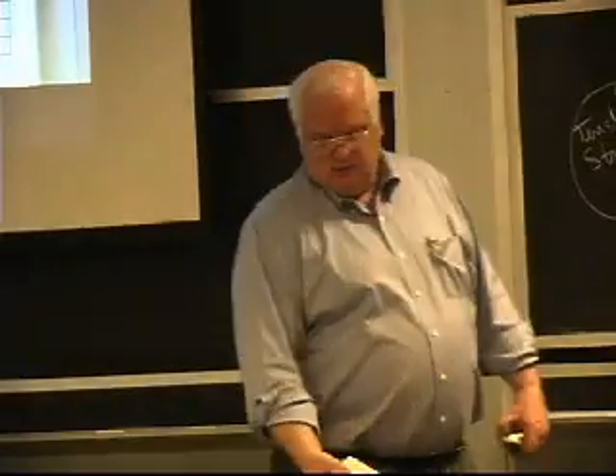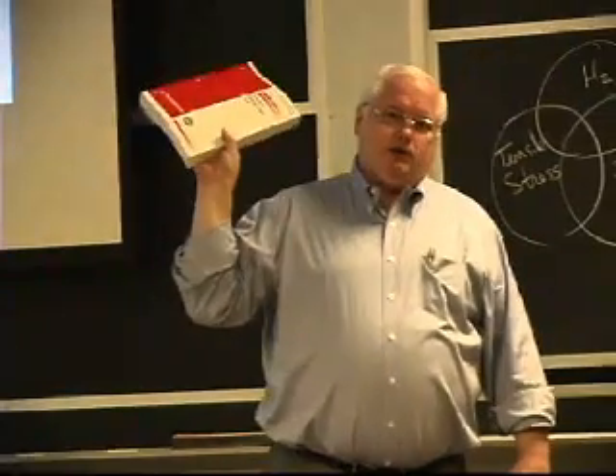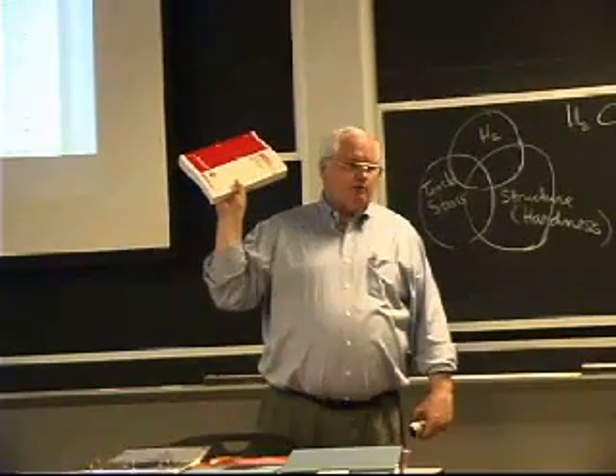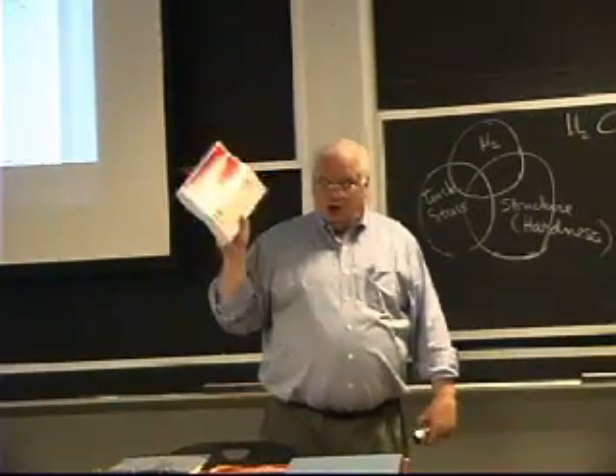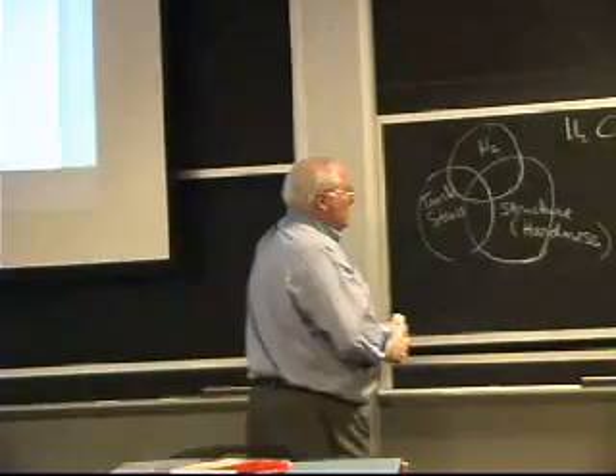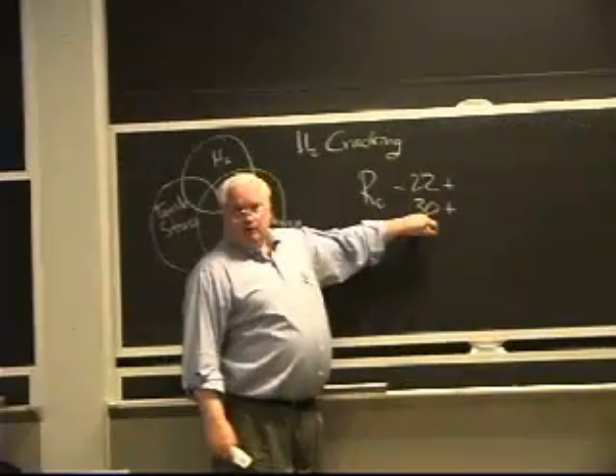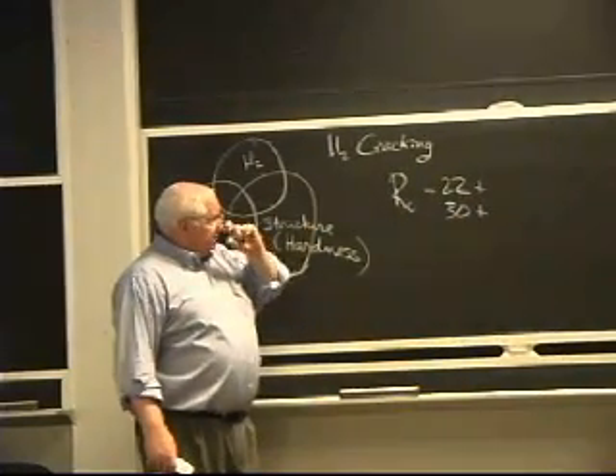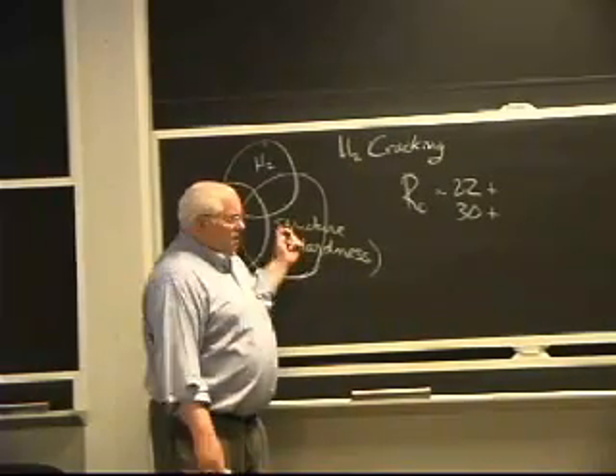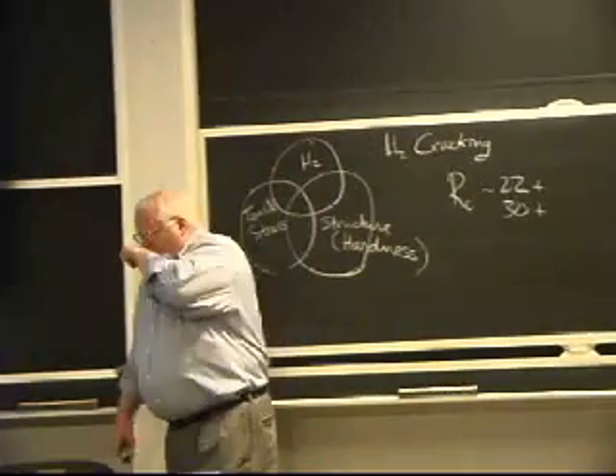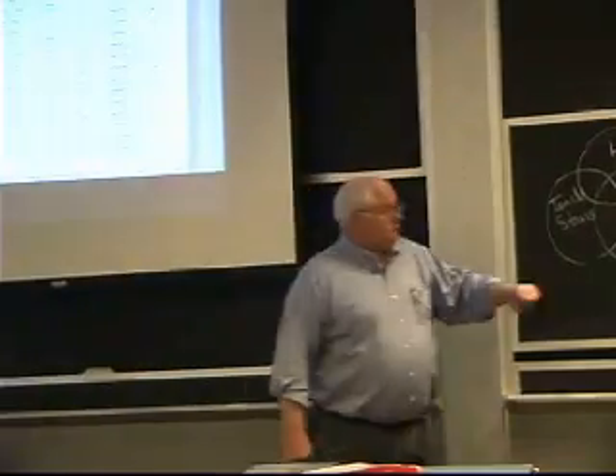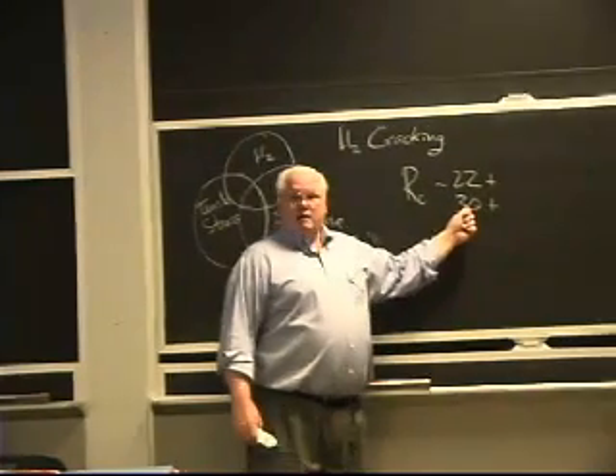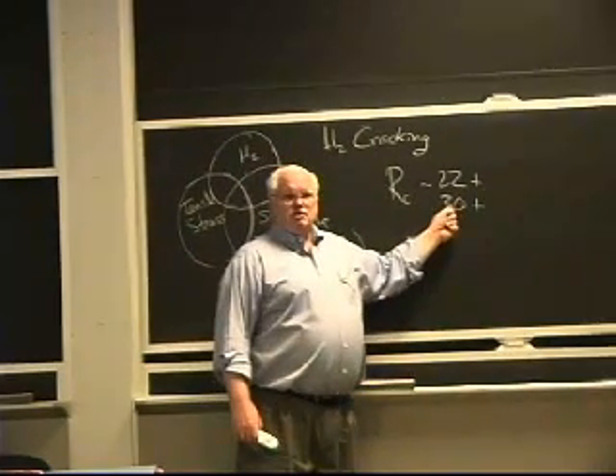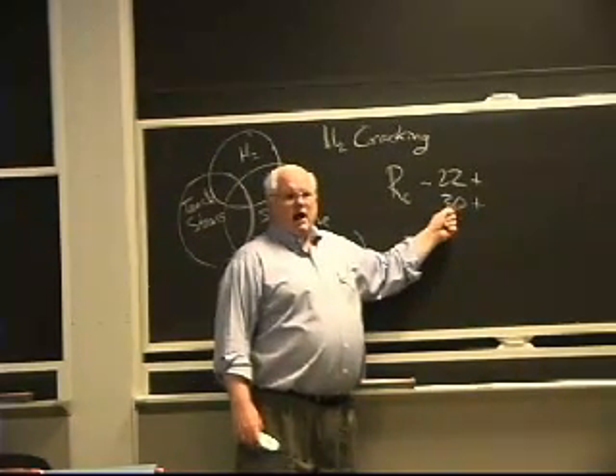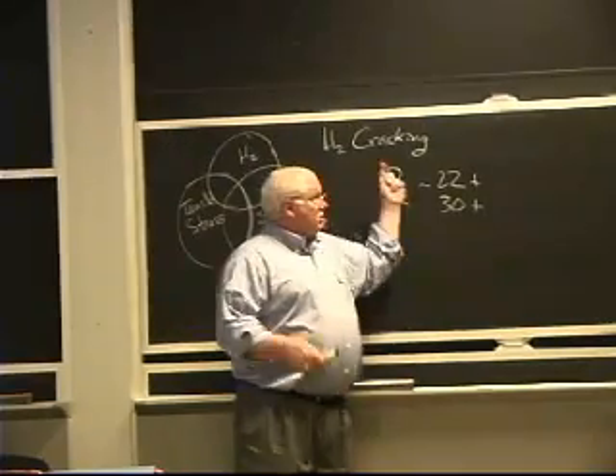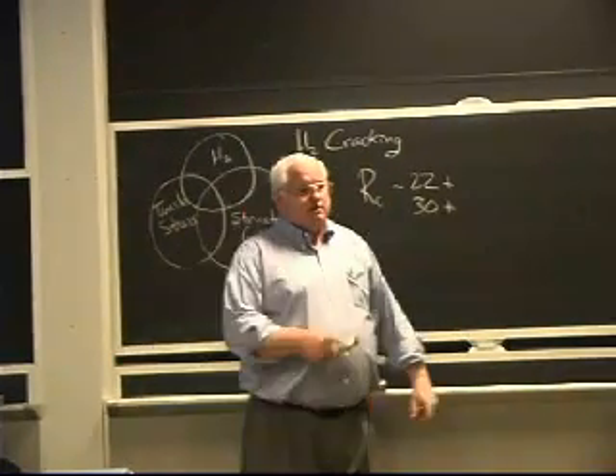In this structural welding code, the highest strength steel you can use is 100 KSI, okay, for bridges and whatnot. But if I'm going to do testing on that, that's going to be a Rockwell C30. It's going to be fairly susceptible to hydrogen cracking, and they won't let me do the non-destructive testing until 48 hours after I finish the weld, just in case I have delayed cracking from hydrogen.